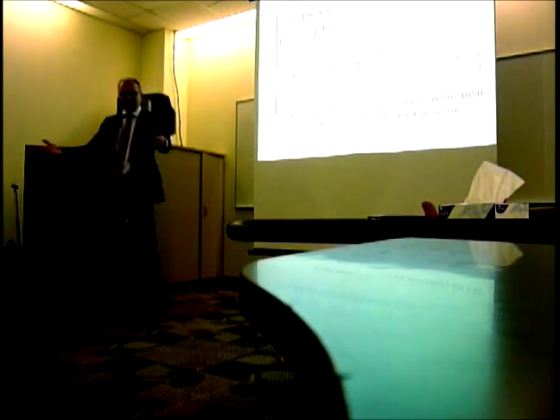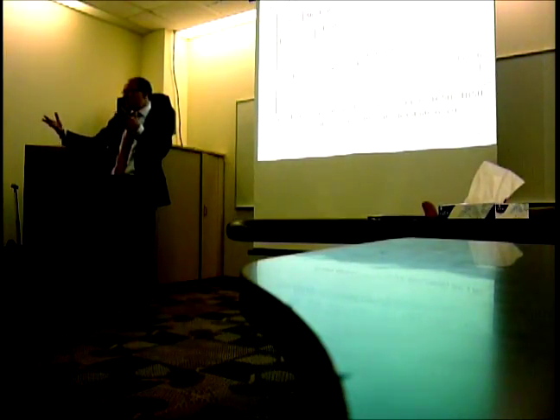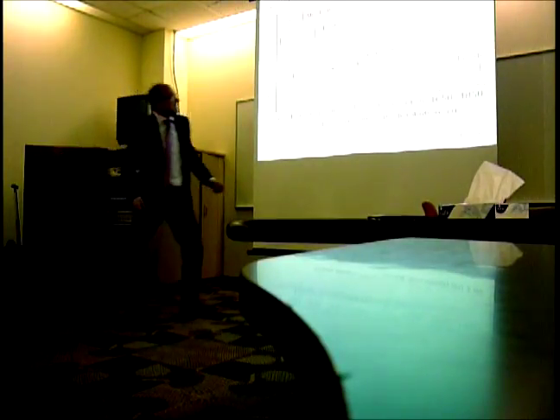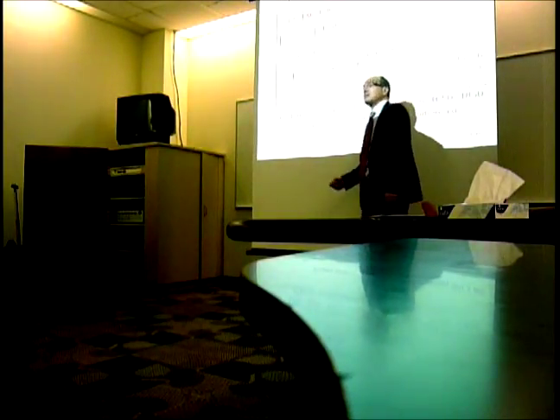So that means that we are now able, with such a sample, as I said, we are all different. Assume we are all ECAT particles, but we have an age distribution. One is a bit younger, the other is a bit older. The one is more active, the other is less active. And so what you can do is, for every particle we can put an activity on. And that seems to be correlating with real catalyst activity.